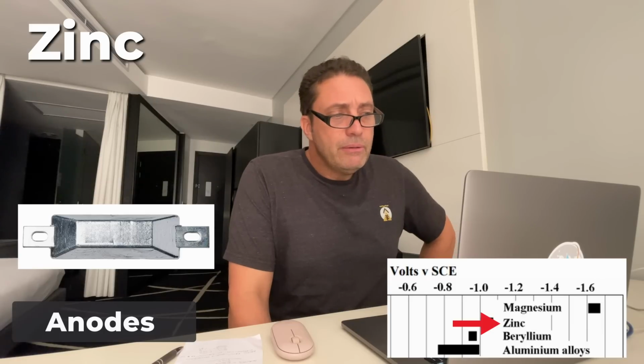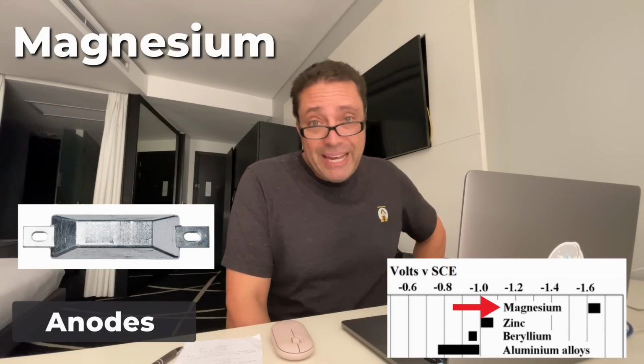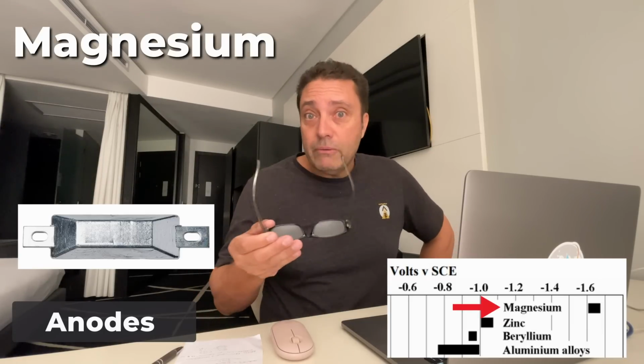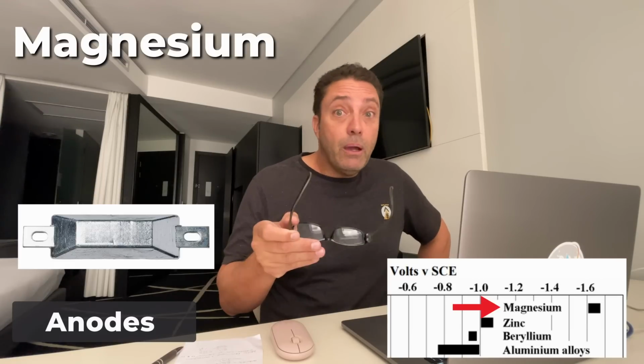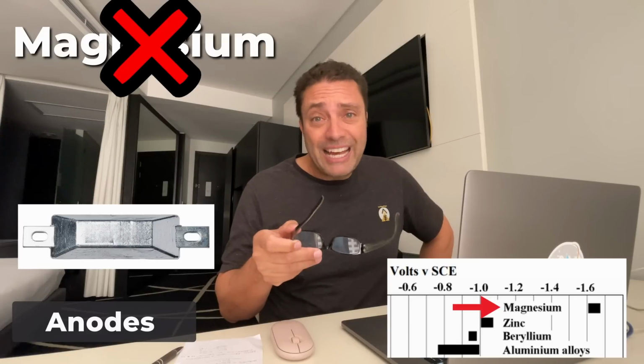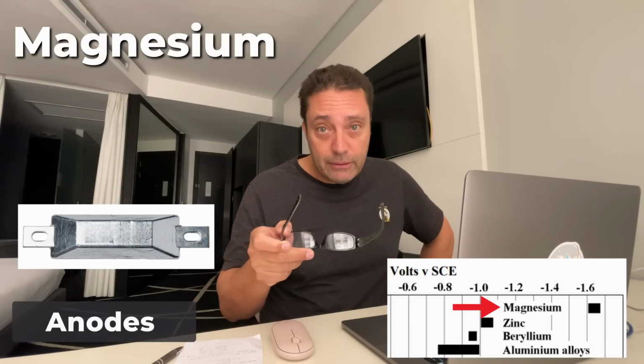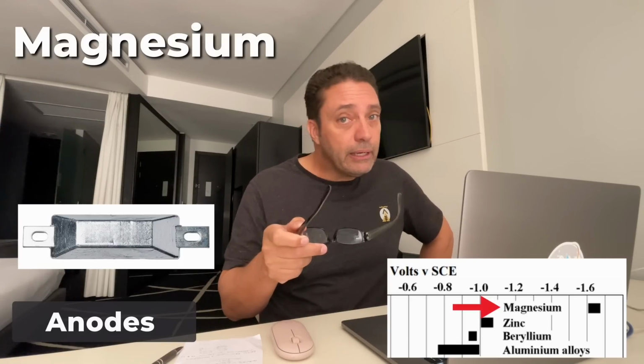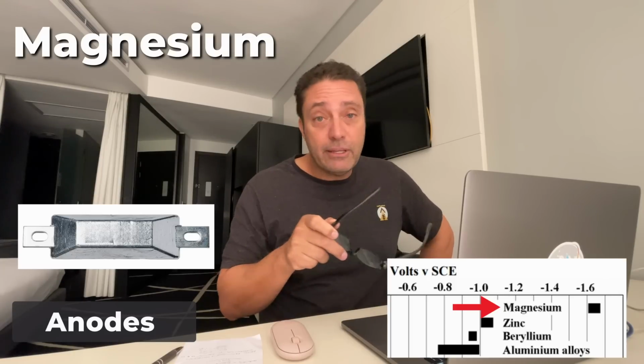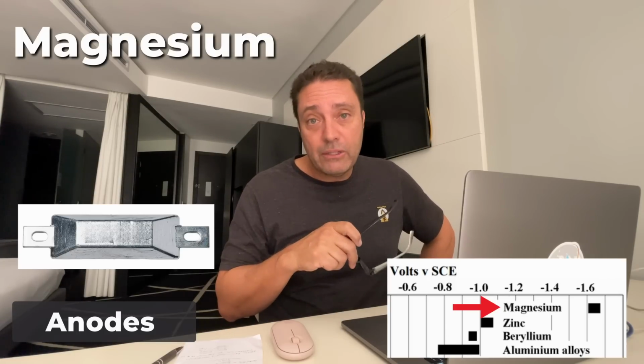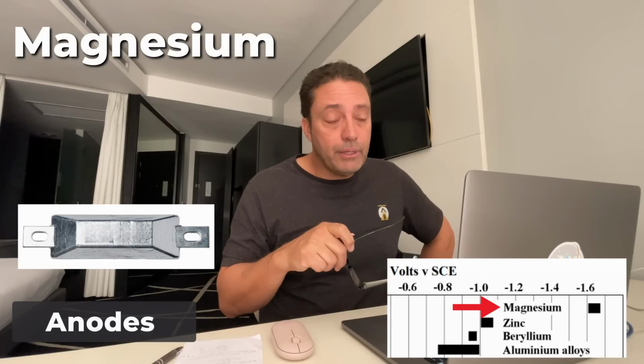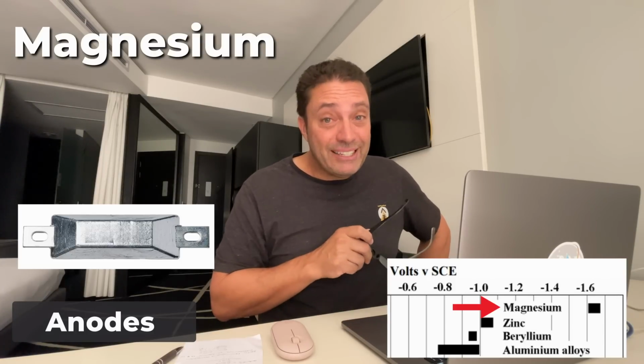Why wouldn't we use magnesium? It's even better at giving up electrons. Wouldn't it be a better anode? No. Why? Because it won't last very long. It's too fast. It'll decay too quickly. I am generally replacing zinc anodes about once a year in certain areas on the boat. Magnesium, you'd probably have to replace it every month.